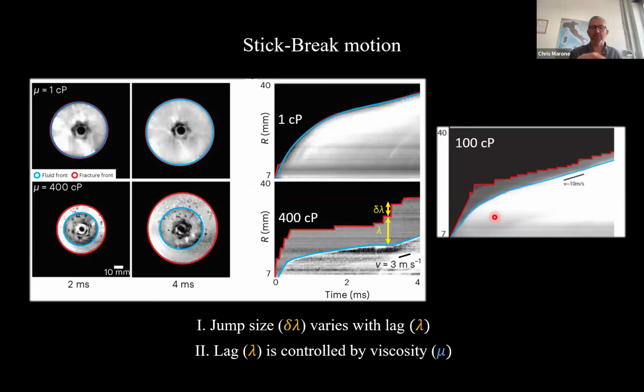I see. What happened is that Thomas was able to load, or to compress, the fluid. It reaches 50 megapascal. So before the crack starts propagating, before it nucleates, the fluid is actually compressed. So the motion of the fluid is purely the decompression of the fluid, with some contribution also due to the elasticity of the tubes and the medium itself. But the pump is irrelevant at this moment anymore. Gotcha. Thank you.